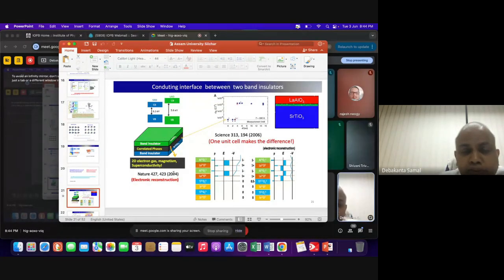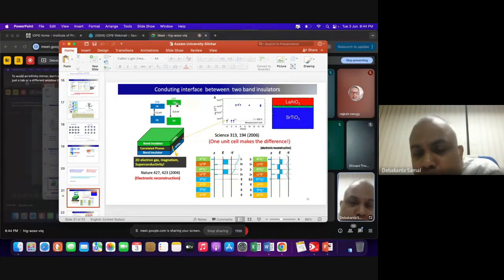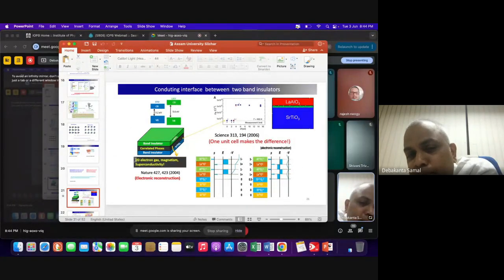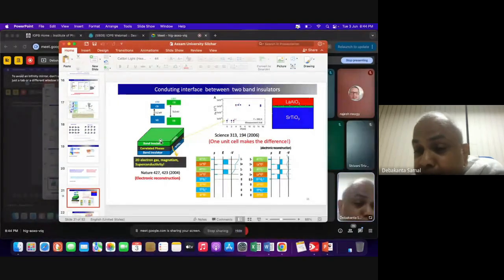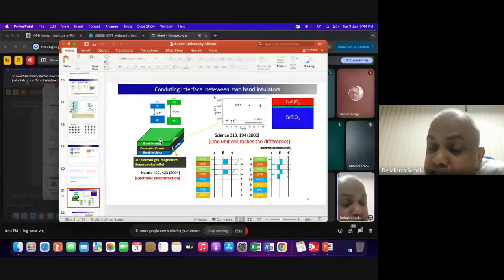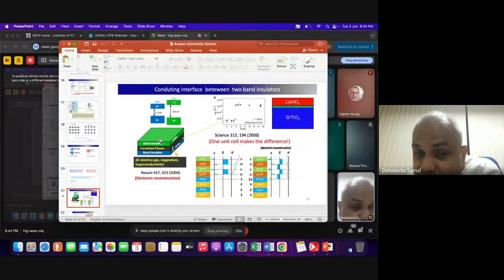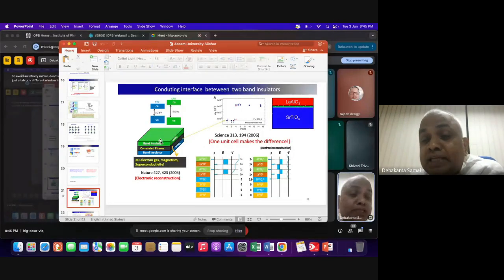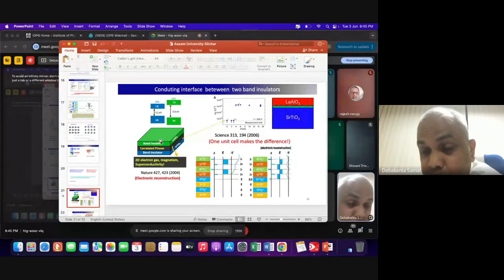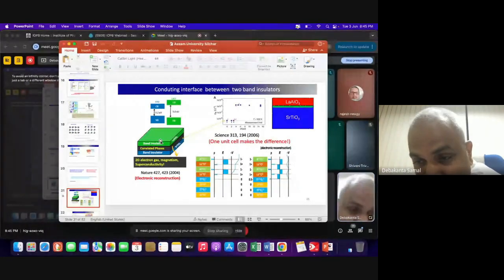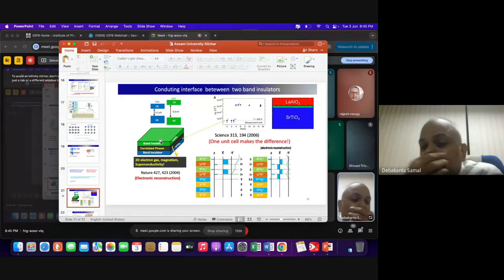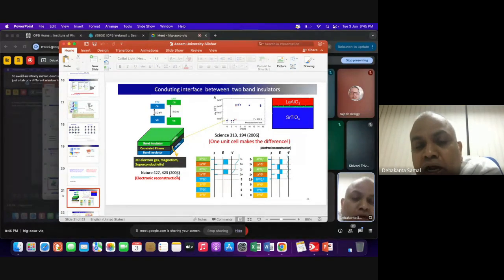But what people found in this 2004 Nature paper is the following. When you put this material on top of the other, at the interface they found a 2D electron gas. It conducts. Surprising, because there are two insulators, but at the interface it conducts. And these insulators are non-magnetic, they are not magnetic. But surprisingly, the interface was found to be magnetic. And also surprisingly, although these are insulators, we found superconductivity. This was very unexpected, and it completely revolutionized this field: by putting together two insulators which are not magnetic and not superconducting, at the interface you are able to get superconductivity. So this started in 2004.